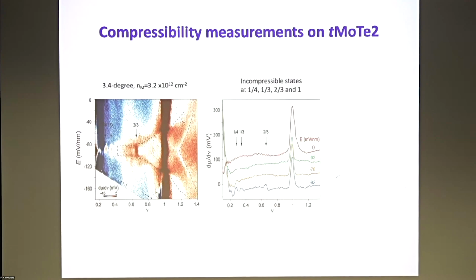And then here on the right-hand side, I just make a few line cuts. The blue curve here is cutting exactly across the zero electric field where the bands are expected to be topological. And you see a few incompressible states, for instance, a very strong one at filling 1, one at 2/3, 1/3, and 1/4 filling factors. So there are fractional states. And once you apply the electric field to just exceed this region here, the -1 incompressible states survive, but the other states are gone, more or less. Okay, so those are the other curves here.